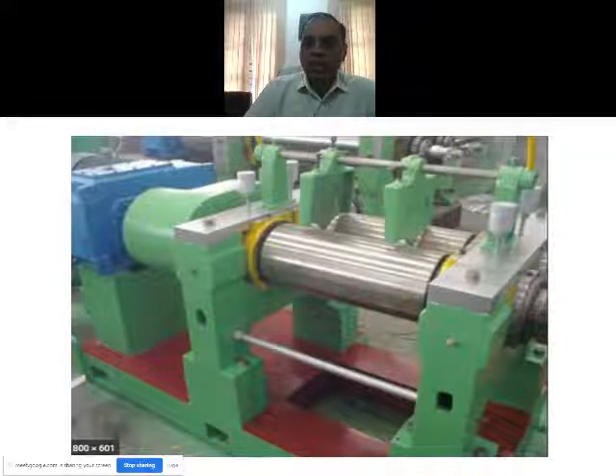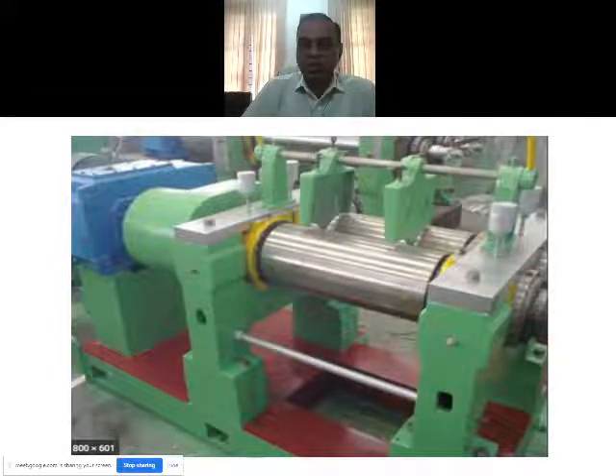So once you have the band, then you can start adding all the ingredients which you have already pre-weighed and kept ready. The whole secret is, every batch has to be mixed in the same mixing time, because the more mixing, the more time it takes before it is dumped, it's sheared to higher and higher extents. That leads to more and more reduction in viscosity, and then the sample consistency will be the casualty for such a mistake. So what's important is to keep the mixing time uniform.